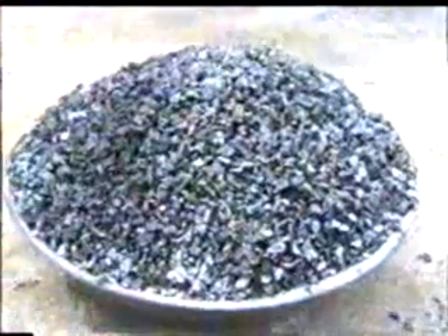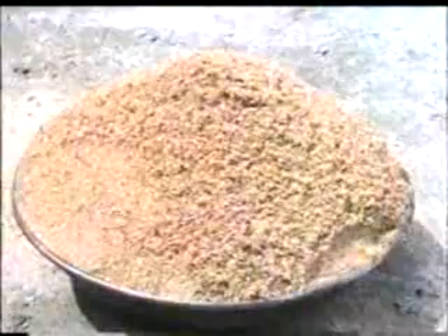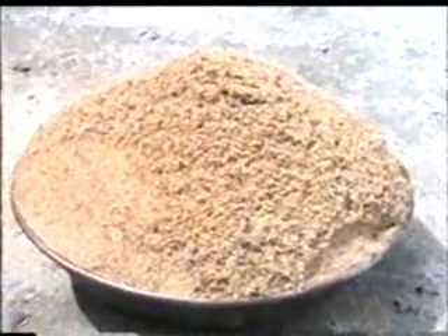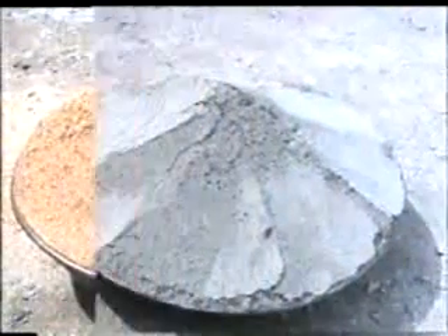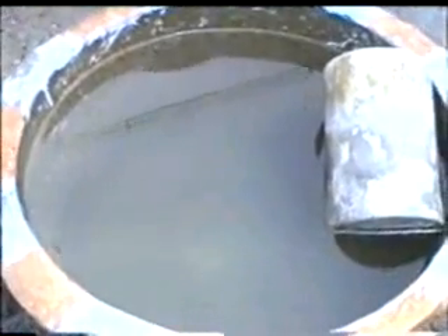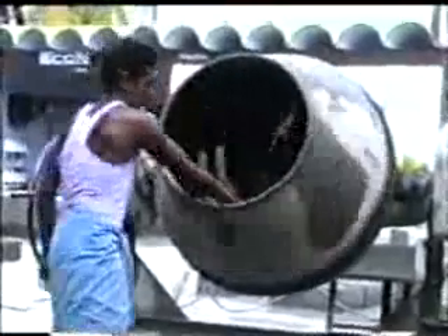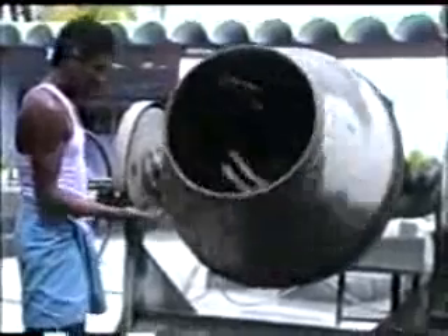Hollow block raw materials are chips, 8 to 12 millimeters, cement, OPC 43 grade, fine sand, and stone dust. The concrete hollow block production process involves 4 steps. The water-to-cement ratio is between 0.45 to 0.5 per kilograms of cement. For 1 metric cube of hollow concrete block, 300 kilograms of cement is required, 0.45 metric cubes of sand, and 0.95 metric cubes of chips. The consistency of the mix should be such that it will cohere when compressed in the hand without trace of excess water.